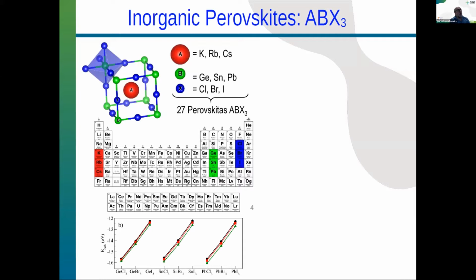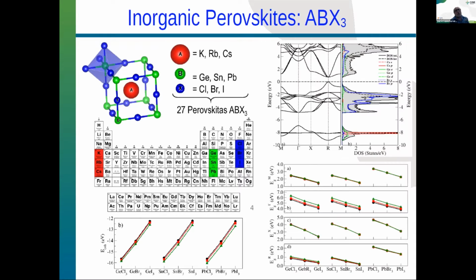But as you can see, when you change the monovalent cation, the difference in the cohesive energy is basically almost null. There's not too much difference. It does not affect the stability, but the halide really plays an important role. And then, having looked at the stability, we move to the electronic properties.